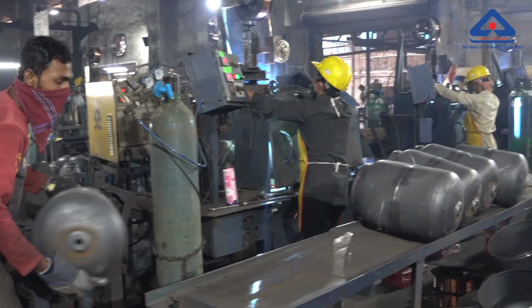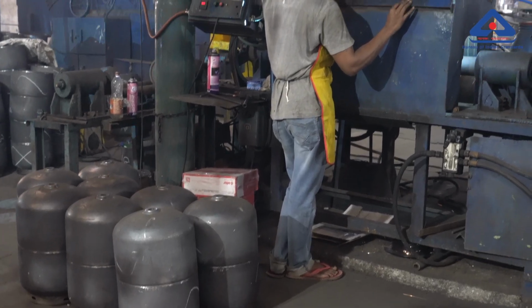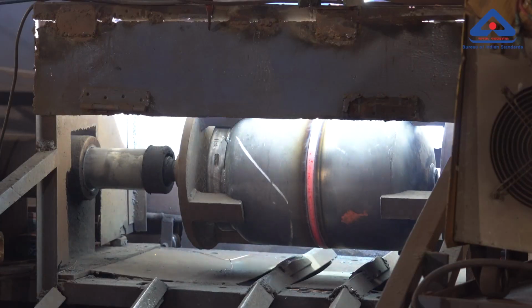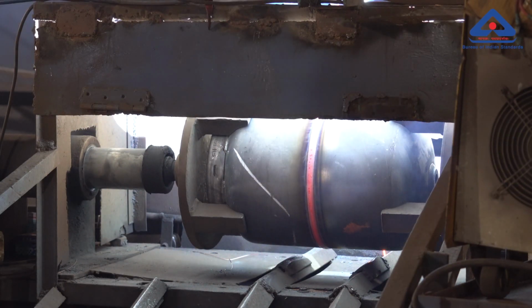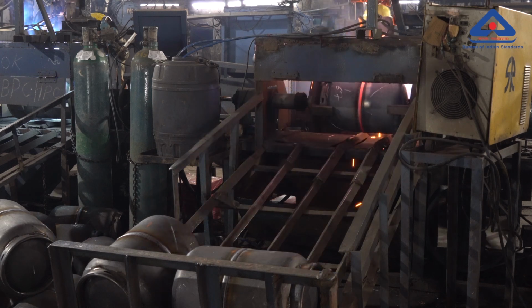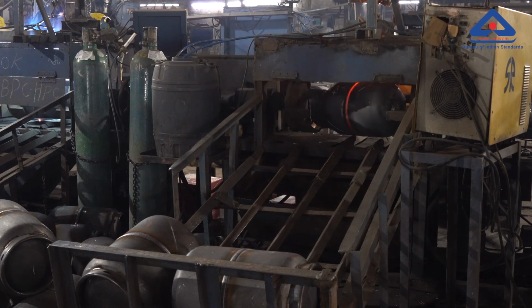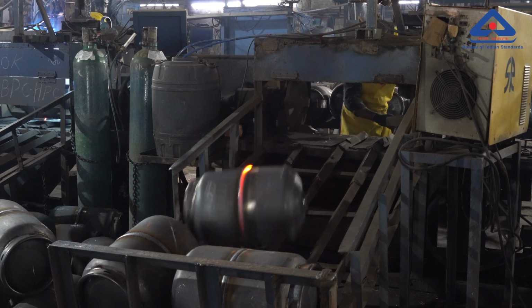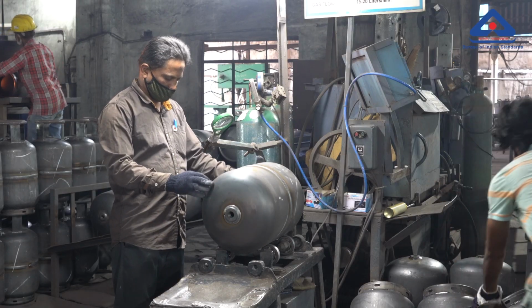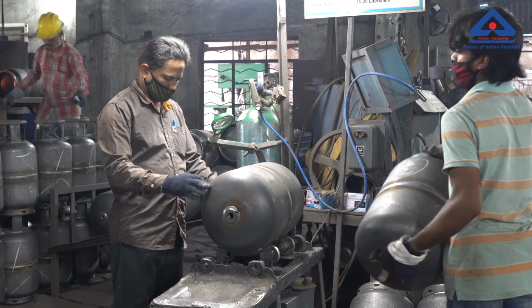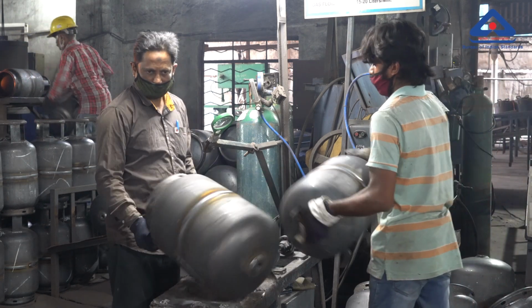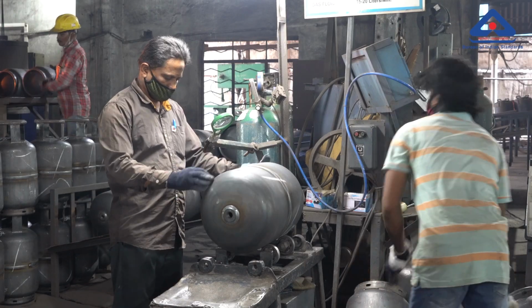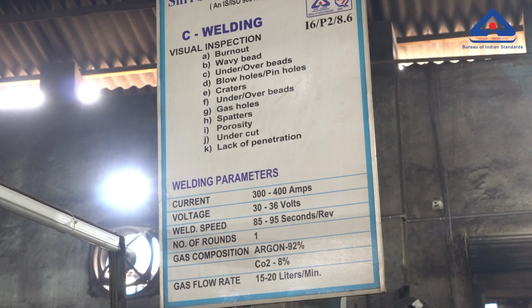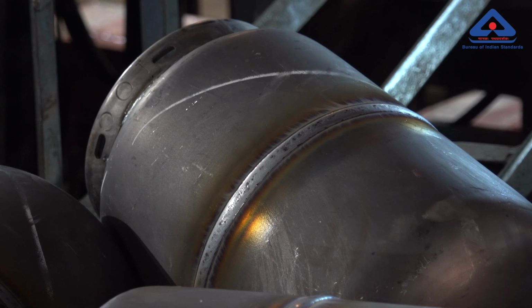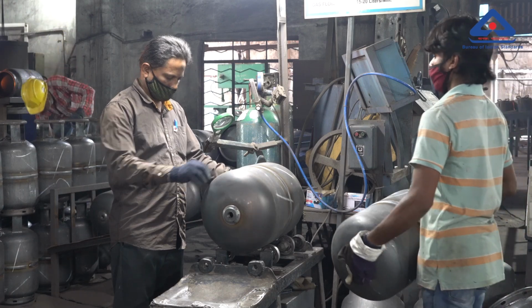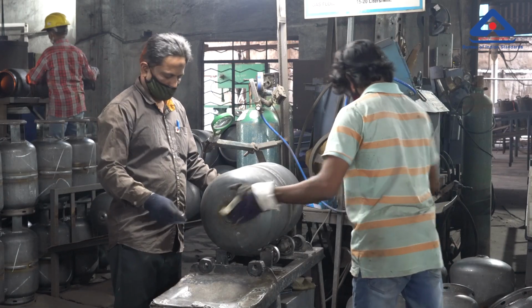After the buffing, they are welded for the circumferential joint in the automatic MIG argon gas welding machine. The circumferential welding is the heart of the manufacturing process, and it is a very important inspection point where defects, if any, like burnouts, wavy bead, pinholes, craters, gas holes, spatters, porosity and lack of penetration are closely checked.